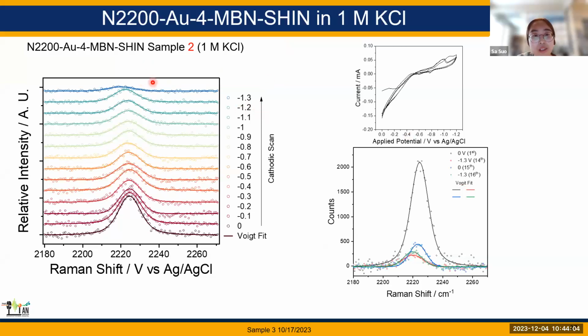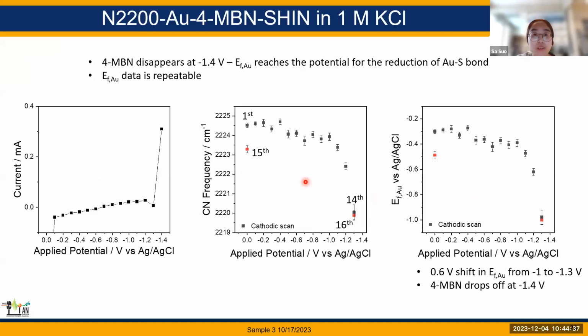Before that, I will show you another set of data where I used the same recipe, so basically repeating the experiments. If we apply potential at 0 and then directly to -1.3 and then back to 0, we can see that the nitrile frequency will first have a red shift and then a blue shift and a red shift. So I think the nitrile frequency is actually doing its work to record the electric field, and it is pretty replicable. This is the summary of the second set of data. We can just look at the right figure, where the Fermi level of gold has a pretty good plateau, and then after the reduction starts, the Fermi level of gold starts to shift. So I think what we saw is real.